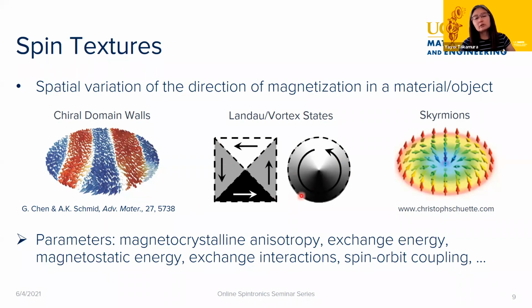And what we'll find is that there are lots of different magnetic parameters that we need to consider in order to understand or predict which states are going to be the stable states. So not only is it shape anisotropy driven, but we have to care about magnetocrystalline anisotropy because these are all epitaxial films, exchange interactions, and different spin orbit coupling as well.